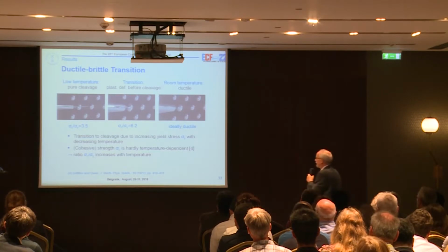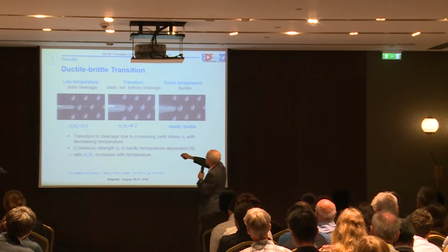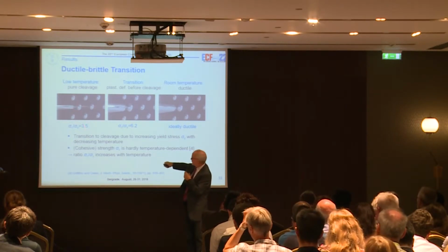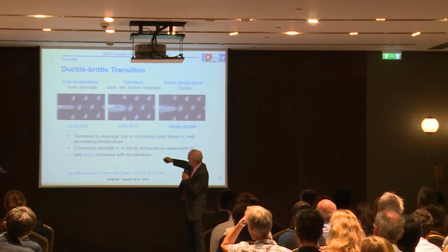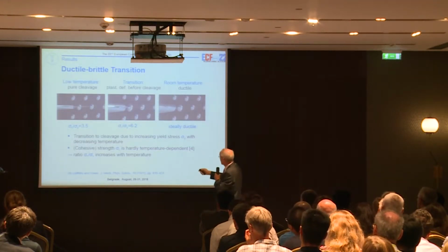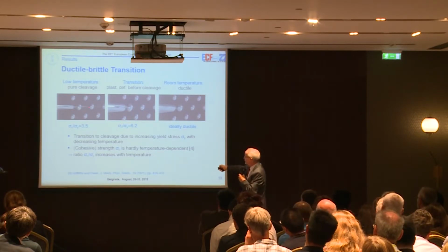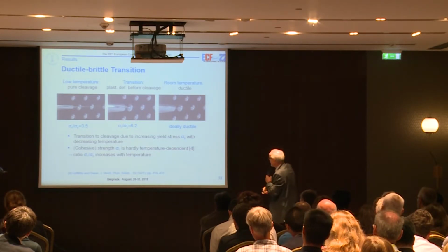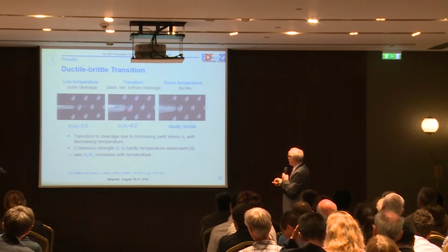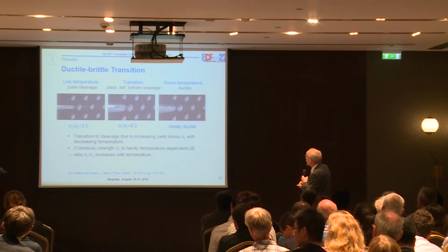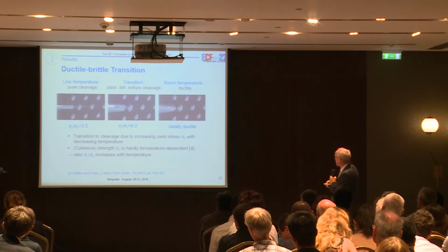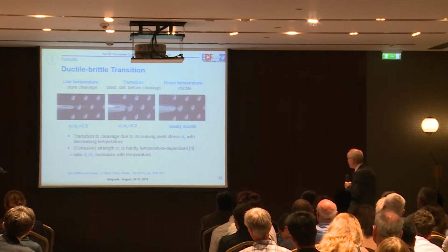Here you see we simulate the transition regions. In the low temperature range for this ratio, we have no blunting, pure fracture of the matrix. The crack may become even unstable. Here we have a little bit of blunting, debonding of the voids, growing of the voids, and then cleavage in the matrix. And this is the pure ductile behavior, which I have shown you before.